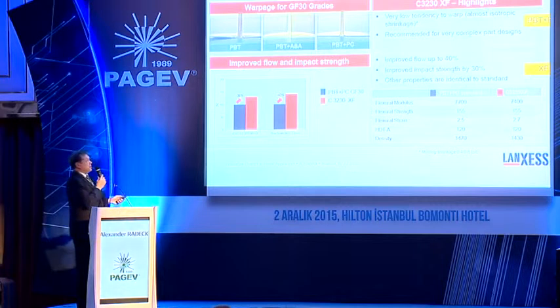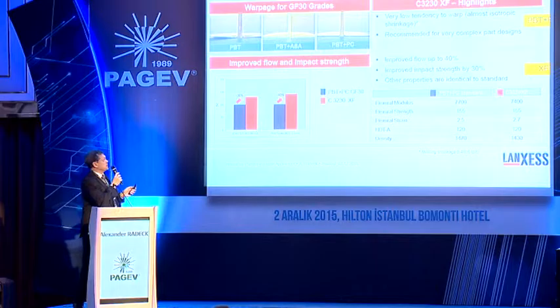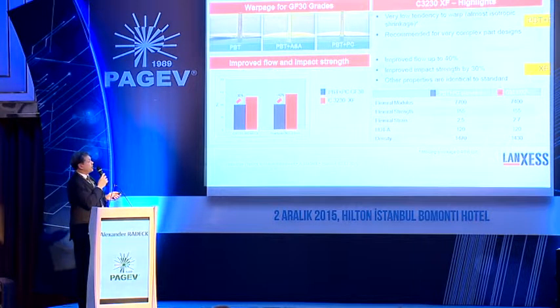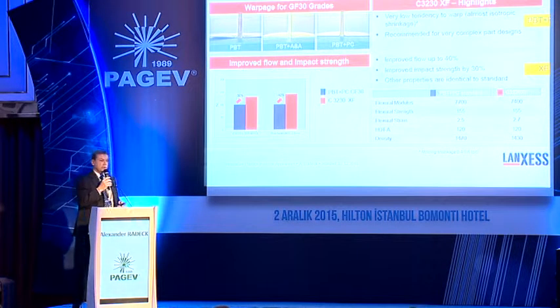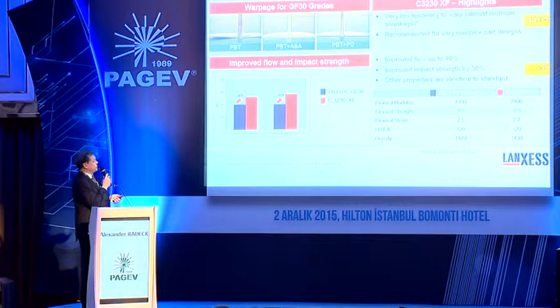See here, why is PBT PC chosen? Here you can see on this simple photo, a round plate with a central sprue, and with a classical PBT glass fiber reinforced, you get this typical Chinese hat. That means that the corner, due to the orientation of the glass fiber, has different shrinkage values, and that gives this bending of the test plate. With PBT ASA you have already a visible improvement, but the lowest tendency to warp you achieve is PBT PC, and that was the reason why this compound was chosen here.